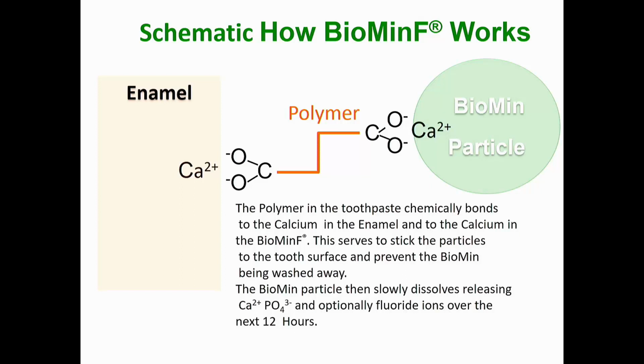In order to prevent the glass particles being washed away in the same way the fluoride is washed away, we need to stick the glass particles to the tooth surface. And the polymer in the toothpaste is polyacrylic acid, which has carboxylic acid groups which chelate calcium ions in the enamel surface and also calcium ions in the glass particle surface. So the polymer serves to stick the glass particle to the tooth surface and prevent it being washed away, and then the glass particle will dissolve over 10 to 12 hours in the mouth, releasing calcium and phosphate, and in the case of the Biomin F, fluoride ions as well.